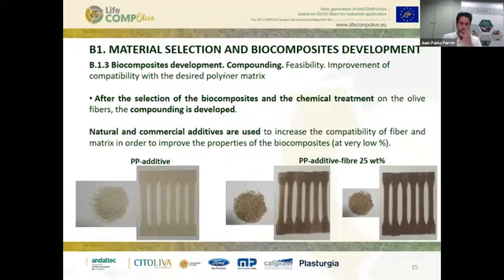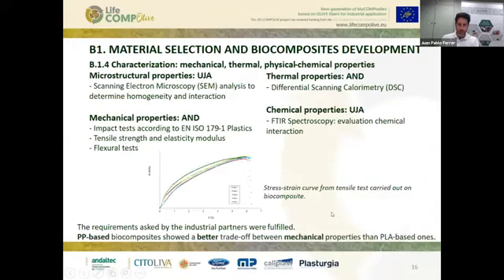Then we optimized also the fabrication of the compounding, and for that we applied some natural and commercial additives in order to improve the coupling between fiber and polymer matrix. We can see here some probes, on the left without fiber, and on the right with already the fiber within the material. In this case, with 25% in weight.